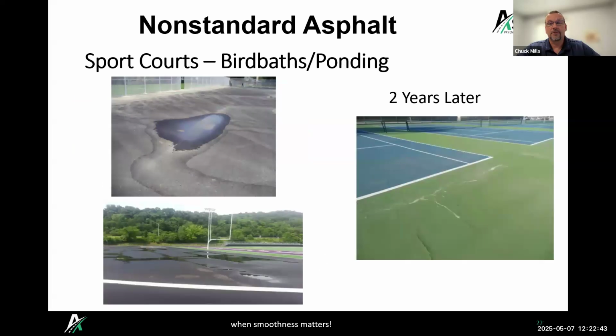So what happens if we don't meet those? We get bird baths and ponding, right? So like I said, it's very important. If we have these areas, once we put the coating on, and water sitting there, it can degrade the coatings as well. Obviously, we wouldn't want to be putting the coatings on while there's still water on the asphalt surface or things like that. So that's going to just make things more difficult. So slopes and grades are important to get proper drainage.